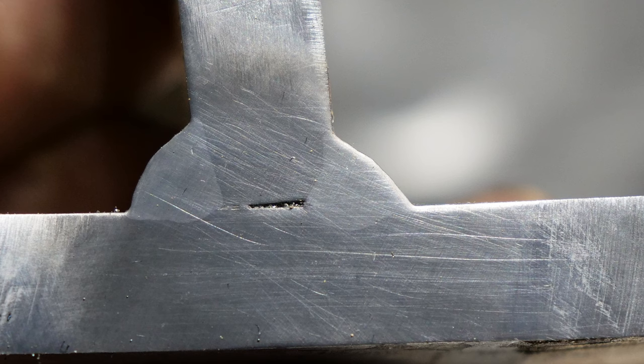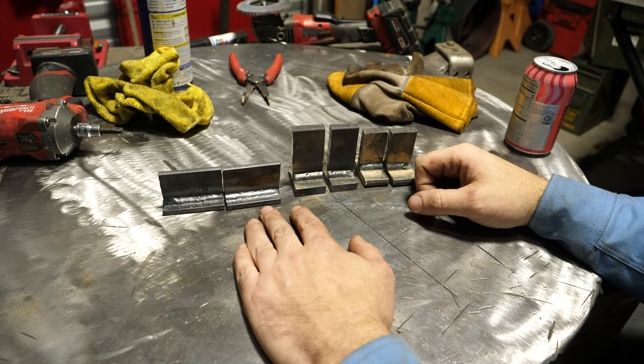The porosity you can generally get rid of. It just takes fine-tuning your settings and your travel speed. If you're not dialed in 100% you can expect a couple pin dots. It's just the nature of flux core wire. That's why when you go to gas shielded and not gasless, that pretty much takes care of all the porosity issues generally speaking. All right, let's go to conclusion.